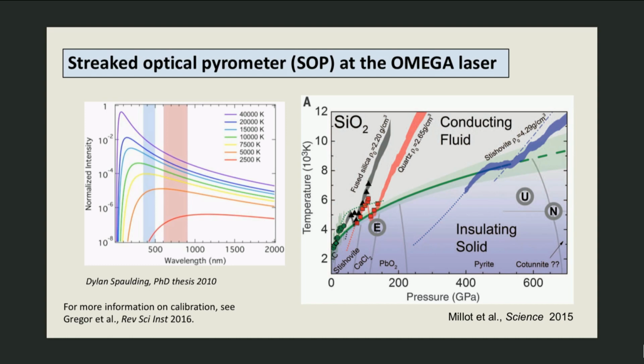And this is a really nice study by Marius Millot looking at different analogs of quartz and how the temperature measurements of those can actually give us constraints on the melting curve of SiO2 across a wide range of temperatures. And so the amount of jog that occurs at that transition is directly related to the enthalpy difference of the two phases.